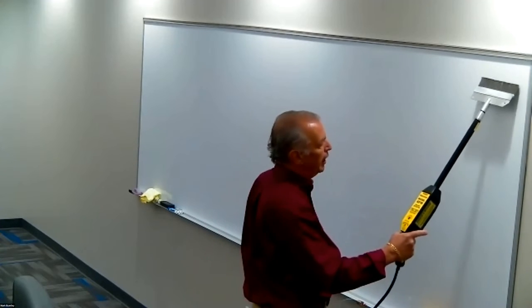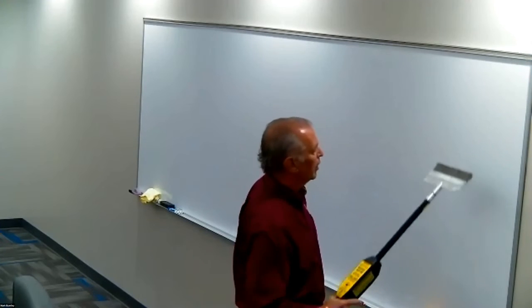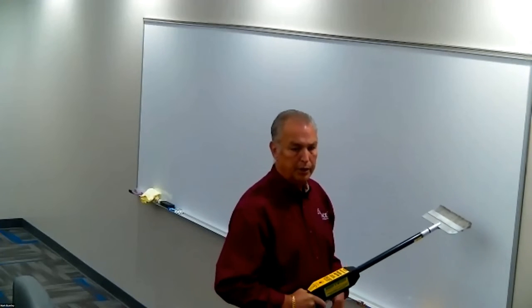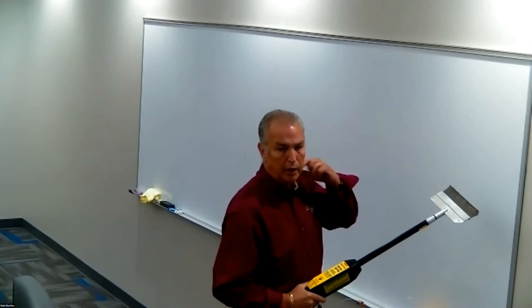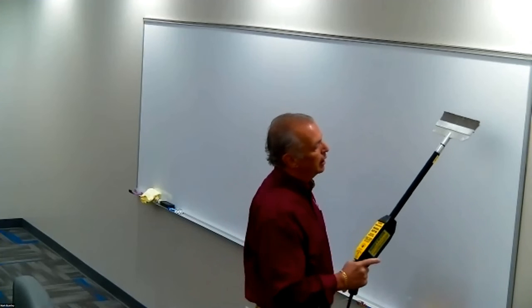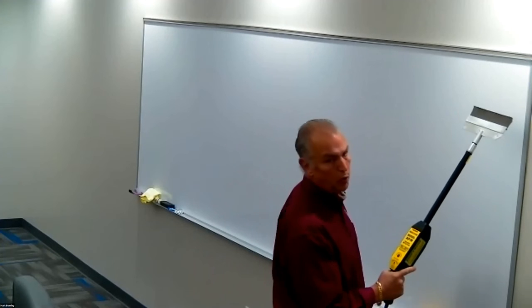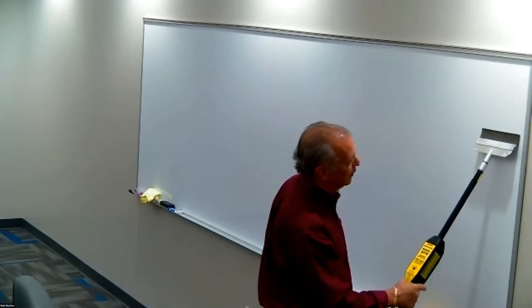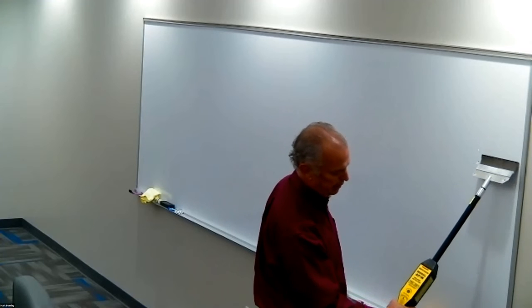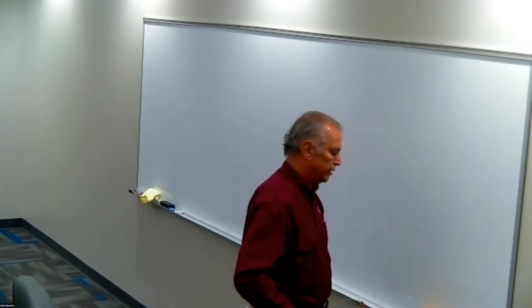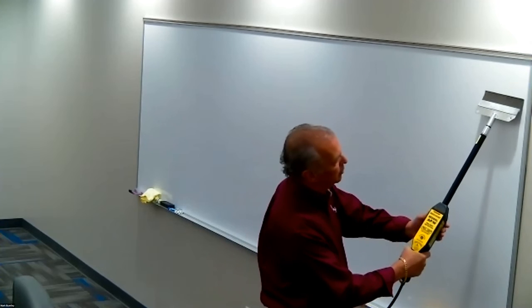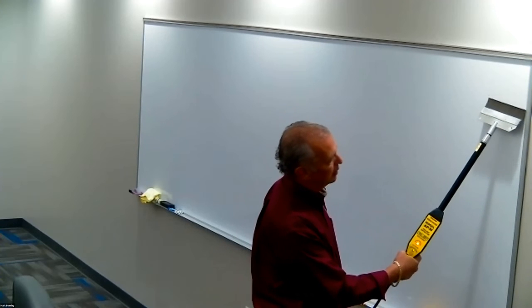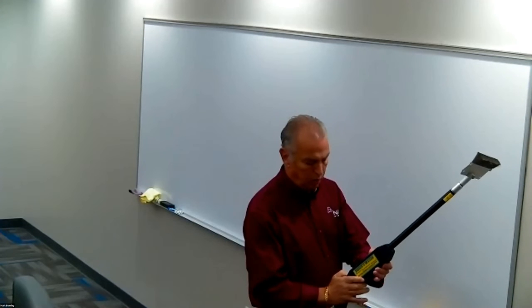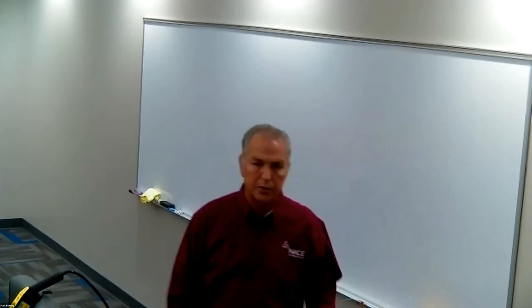You'll note that this is still kind of wet, and even though we get very close, the water won't track pulse type DC. Pure DC will track through the water and right to a holiday that you've tested 3 feet over. So in the rain, we use these quite often in the rain. So again, non-conductive. And then we come over to this edge, and we get a good solid tone and an indicator on the light, and then go back to this ground, and here you go. So that's the difference. We're actually using an arc to bridge that air gap, not water, or water with surfactant. So that is basically the difference between wet sponge and high voltage.